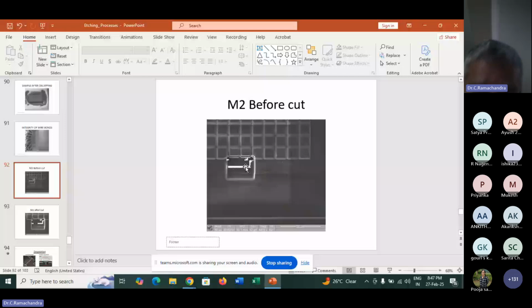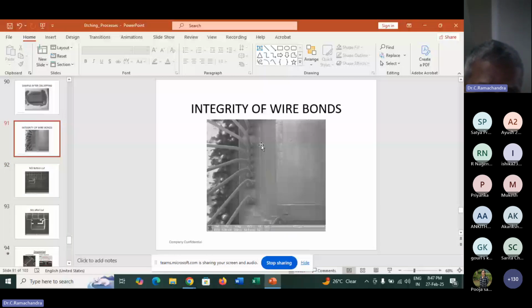The device was not working in the first design. After careful analysis, after studying the GDS, this was found to be wrongly connected. It should have been avoided. That was a mistake. But how do we know it works? So here we etch this metal. This is a few microns only that we etch. Then we do testing. Because we do testing, it is important to keep the wire bond integrity. The wire bond should never get damaged in the whole process.